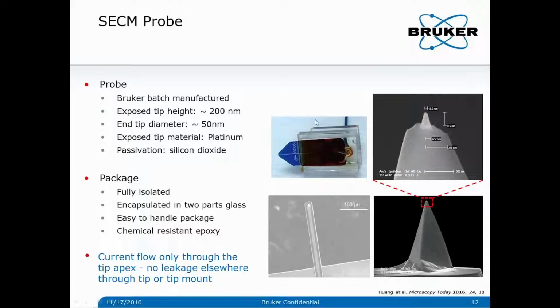The core of peak force SECM is the nanoelectrode probe, because this is pretty much the most critical part of this technique. Here is the pre-mounted nanoelectrode probe, encapsulated in glass and sealed with chemical-resistant epoxy. As you can see, the probe encapsulation was designed to have a relatively large size for ease of handling. You can also see some grooves on the glass housing here. The most important part is the tip apex. The tip apex has a platinum-coated area of about 50 nanometers in end tip diameter, and about 200 nanometers in tip height. Other than this electrochemically active region, the probe is fully insulated by dielectrics, mainly a coating of silicon dioxide. With this design and packaging, current flows only through the tip apex and there is no leakage elsewhere.